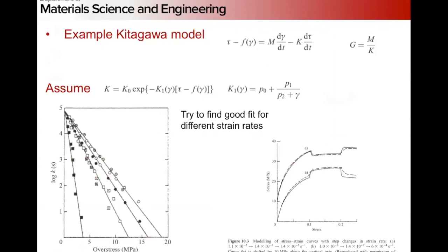So that's basically what they did here. So they expressed K here in this form, right? And then basically you assume a form for this K, then plot the value as a function of overstress. Then you can go back and solve for M, and then you end up with sort of a model that does a good job of capturing these sort of jump